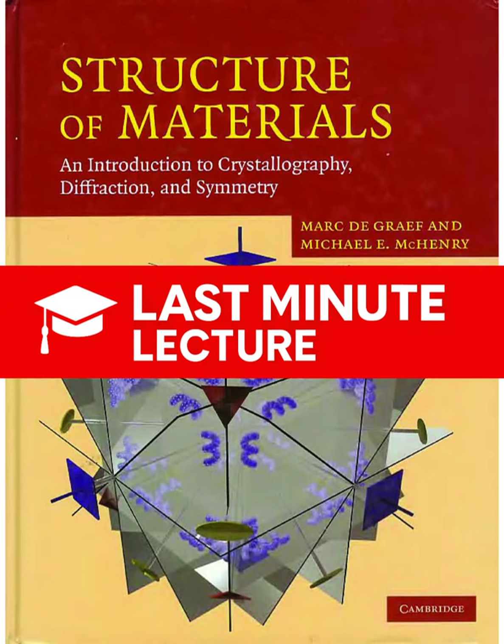So pure SiO2 is a perfect network former. But most commercial glass is impure. We add what are called network modifiers. What are they and what do they do? Network modifiers are typically alkali or alkaline earth oxides like Na2O or CaO. When you add them, they do exactly what their name implies. They break the continuous silicon-oxygen network. How? They can't be incorporated into the lattice, so they wedge themselves into the structure, creating dangling bonds, what we call non-bridging oxygen atoms. And the structural consequence of breaking the network is what?